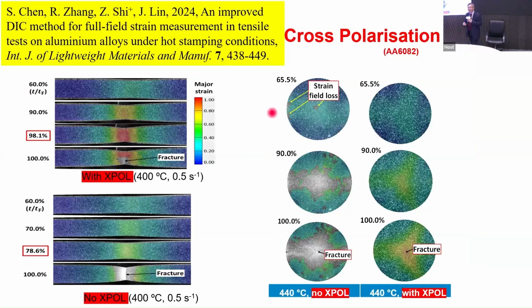And here I give you examples. The results have been published recently, in 2024. This is the aluminum alloy AA6082, and without cross polarization, when we get the data at about 70% of failure, the paint starts to peel off. At 100% deformation, you can see the paint has been peeled off. You can't get the data. But here, with the cross polarization, we get data nearly to failure. For example, at 98% of deformation, we still get good data.